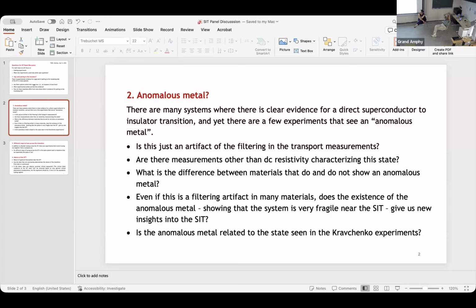So your model is like having a superconductor and, in series, a metal, right? Take superconducting balls and put them in it. Okay, but in the end, it always amounts to what is this surrounding metal. Exactly, a good metal. I don't know whether that is the origin of any of this. The standard theory, as we all know, is that in disordered systems there shouldn't be any metal, with interactions. All systems have interactions. Here Tc goes to zero and you get a metal.